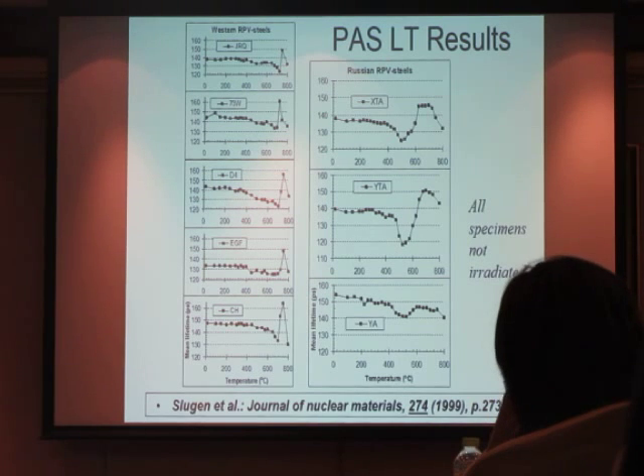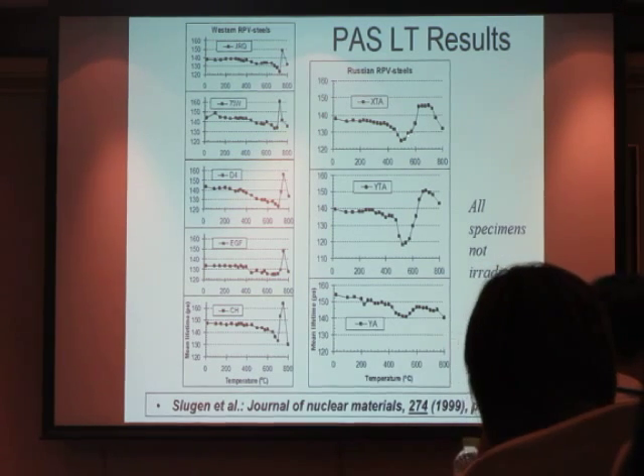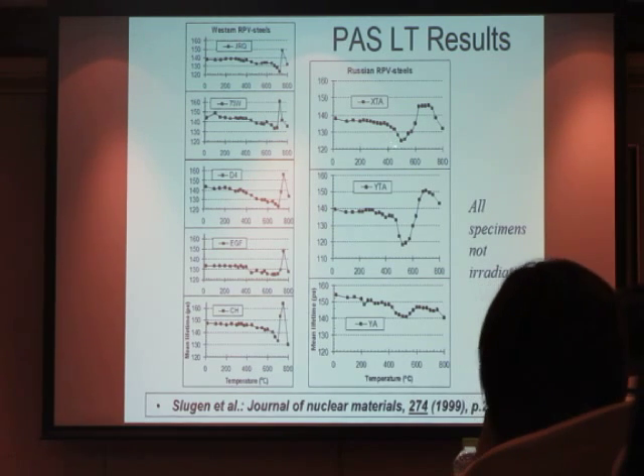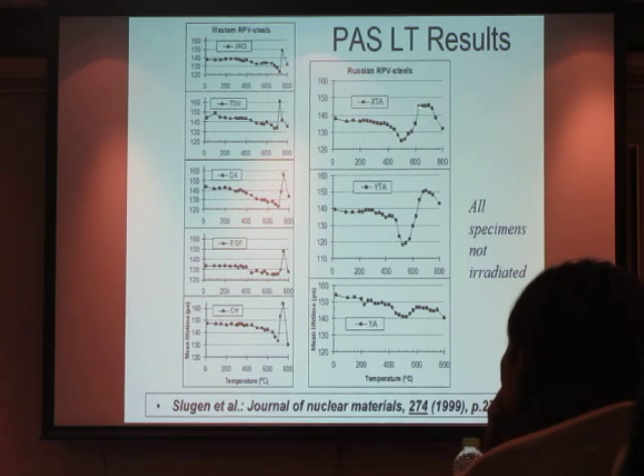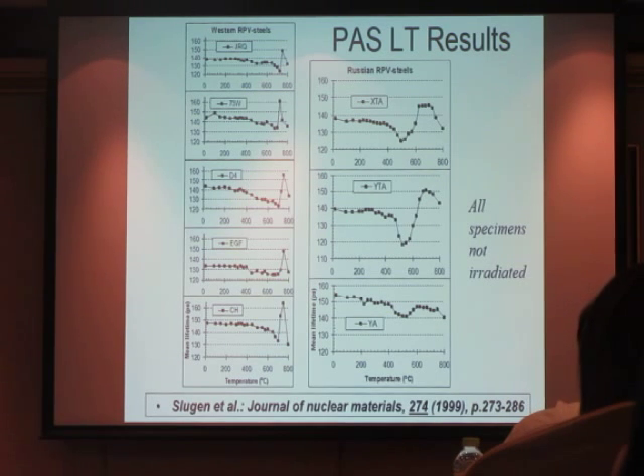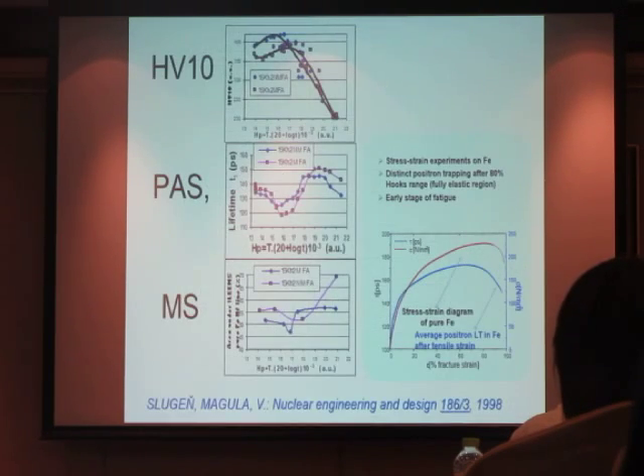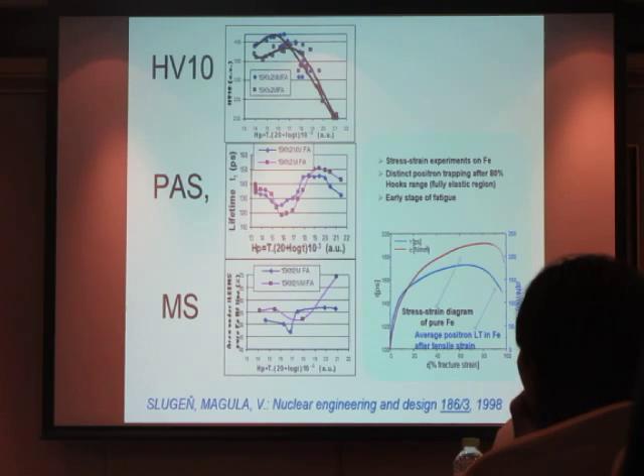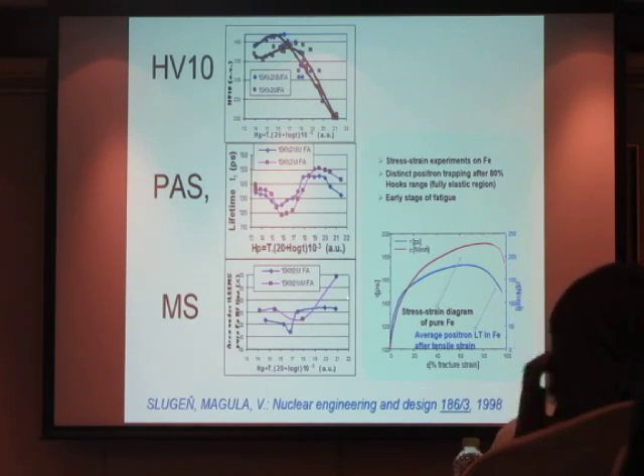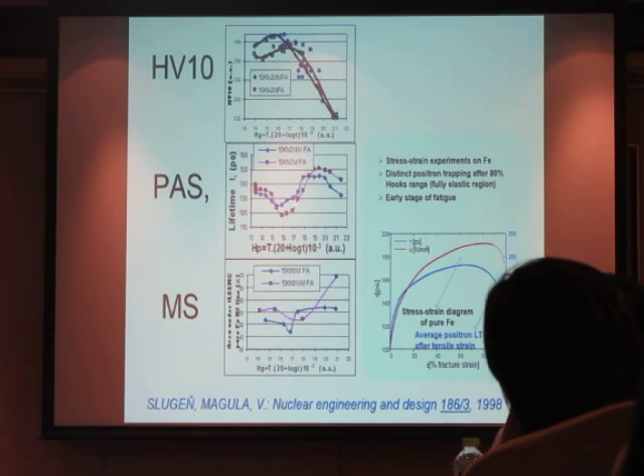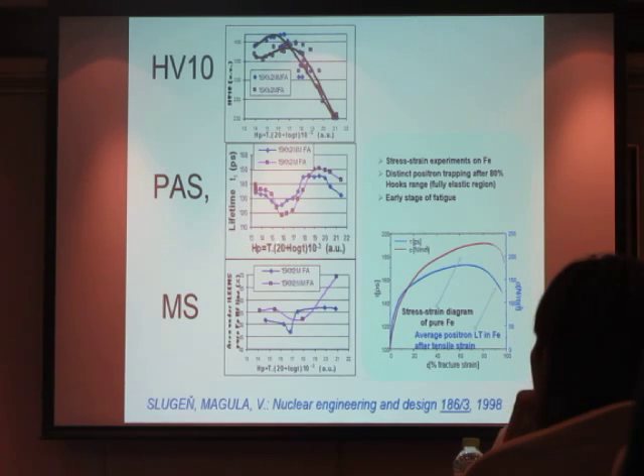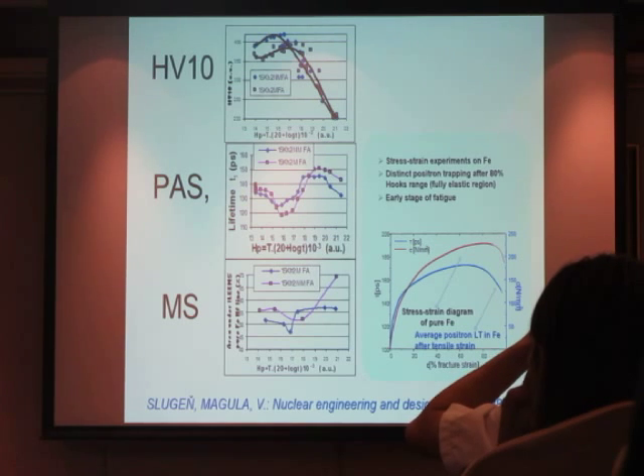Much more interesting are the Russian steels, where there is a minimum at approximately 450 or 500 degrees Celsius, and this increase is connected with the reordering of the structure. There is a hypothesis, which was proved by transmission electron microscopy, about this metal carbide movement. It's not possible to make a statement according to only one technique. Therefore, we try to make a correlation between Mössbauer spectroscopy, hardness, Vickers measurement, and stress-strain measurements, and you see that the maximal hardness corresponds to the minimum of the lifetime of the defect elements if we consider this Larson-Miller parameter which combines time and temperature of the treatment.